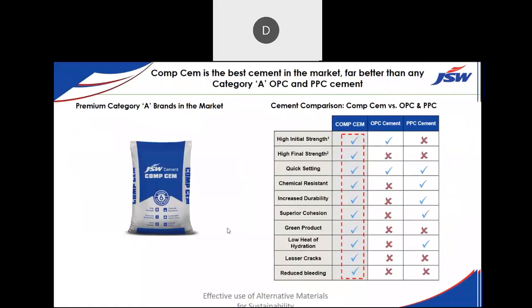There's one more cement called Comp Cem. This is a composite cement using both fly ash and GGBS in the concrete matrix. All the parameters we have cross-checked in terms of high early strength, final setting time, quick setting time, chemical resistance, increased durability, superior cohesion, green product. So all these things we have discussed. Lesser cracks, reduced bleeding. It's a wonderful cement which is now being marketed in Karnataka. The composite cement is very good. People are adopting. It is much more superior to OPC cement, PPC cement. You can see all the marks here with a tick, where the others are like a cross. In all the performance parameters, this is behaving properly.